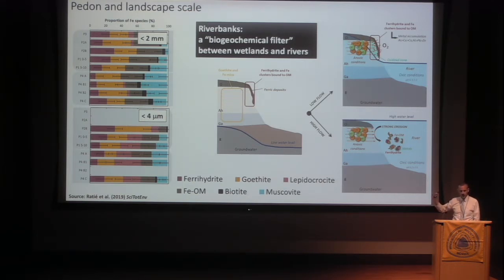And so the surface was primarily oxidized but periodically anoxic, and then a subsurface that was, for the most part, anoxic, but periodically oxidized as well. And as the water table fluctuated, they were able to track changes in mineralogy, both as a function of depth, so the more shallow versus the deeper particles, and then as a function of particle size as well, and could say something about how the iron was distributed. For the most part, in the near surface, iron was dominated by nanoparticles of ferrihydrite and nanophases of iron mixed with organic matter. And then in the subsurface, due to subsequent changeover, there were more transformations occurring, resulting in a buildup of goethite.